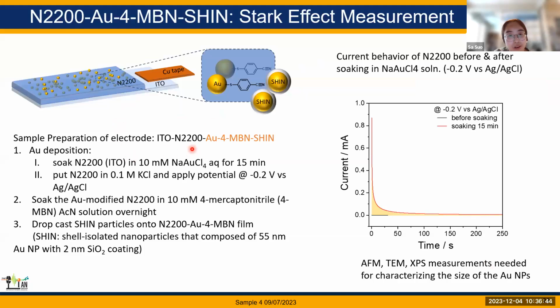So this is our recipe for depositing gold, functionalizing with 4MBN, and then depositing SHINs. Before gold deposition, the current is very small. After soaking the N2200 in the sodium tetrachloroaurate solution and then applying potential at negative 0.2 volts in the KCl solution, we can see a large reduction current which decreases with longer time. Basically, the integrated area here can represent how much gold can be deposited.